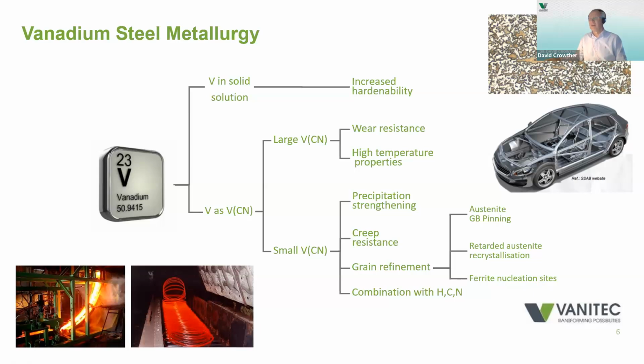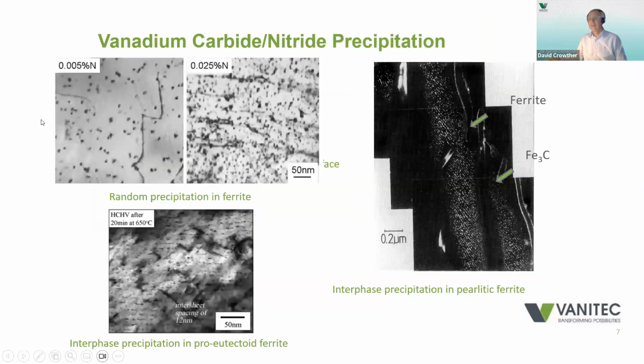properties. They can be present in very large precipitates, for example, in tool steels, where they give wear resistance. The smaller precipitates can give precipitation strengthening, grain refinement, and other beneficial properties. And it's very much the size and volume fraction of these precipitates that influence the steel properties. Looking at these precipitates in a little more detail, this just illustrates the types of precipitates you can get.